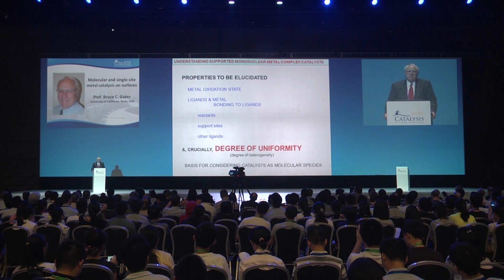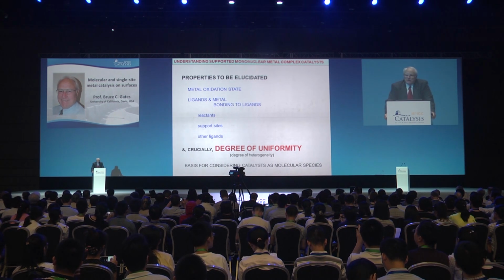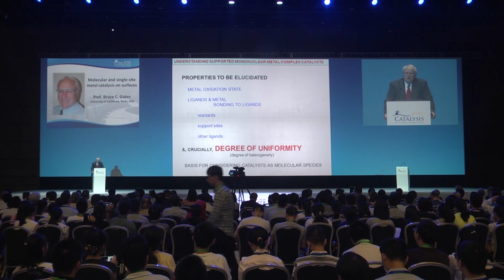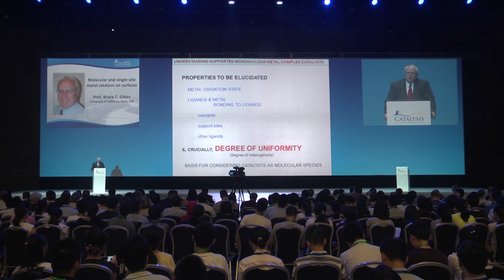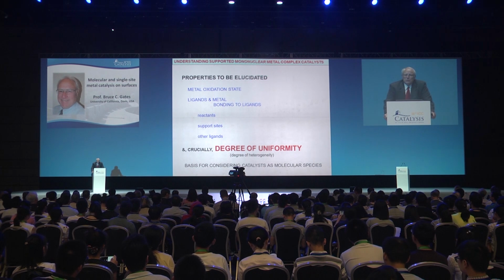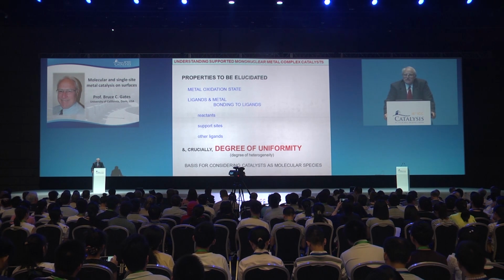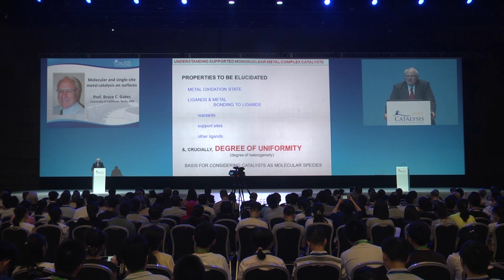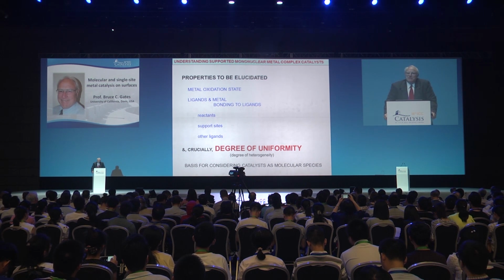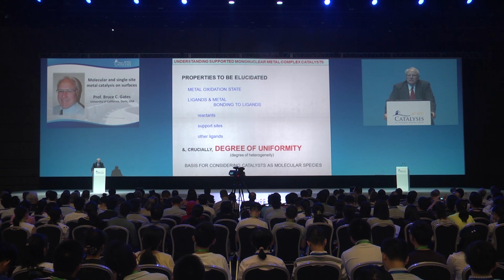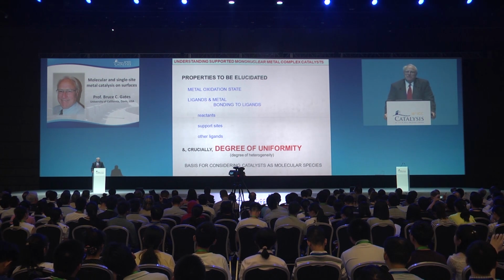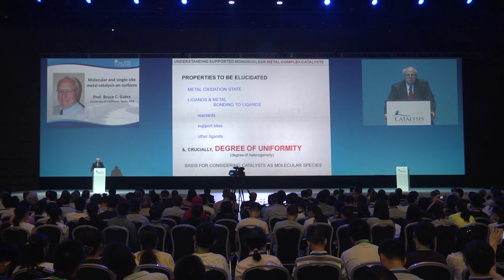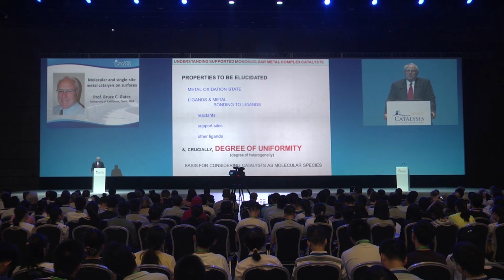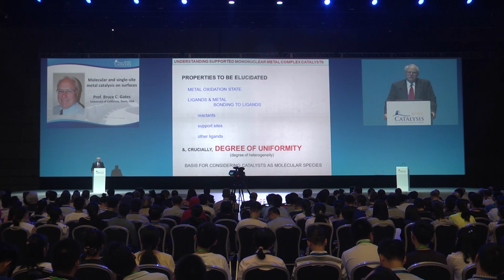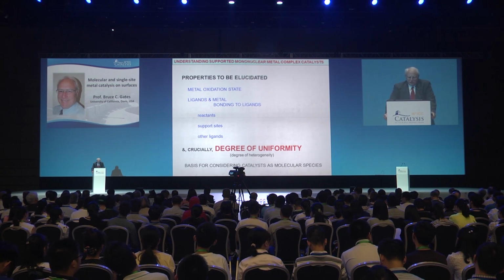But the crucial point here, connected to the precision of the synthesis, has to do with the degree of uniformity of the supported species. We are trying to beat heterogeneity. Heterogeneity is the first statement we make about most solid catalysts, and we make approximations to deal with those catalysts. What we're attempting to do for starters here is make catalysts that are not limited by intrinsic heterogeneity and lend themselves to precise characterization and deep understanding.